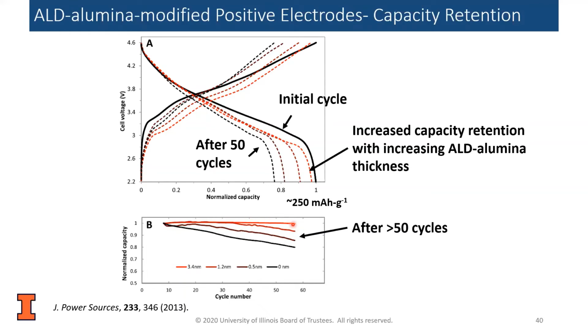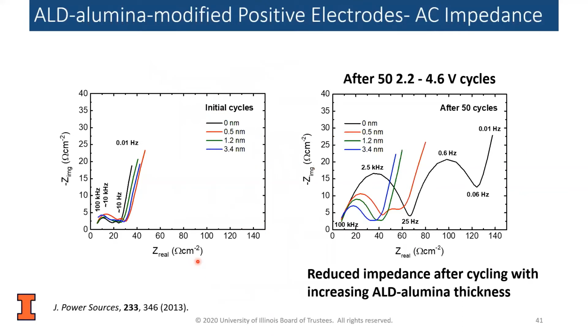capacity. And then the AC impedance shows the initial cycles right here. Very low impedance, which we were happy with. This is actually a little bit lower than we expected. And then after 50 cycles, we see that the thickest layer had the least amount of capacity or impedance increase. The next had a little bit more, then a little bit more, and then finally at the uncoated, we had a lot of impedance increase.